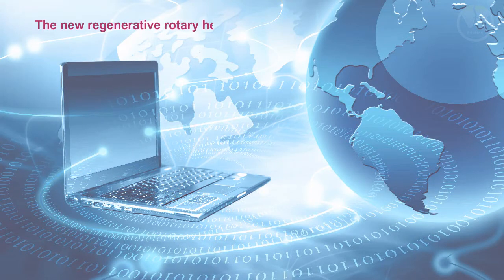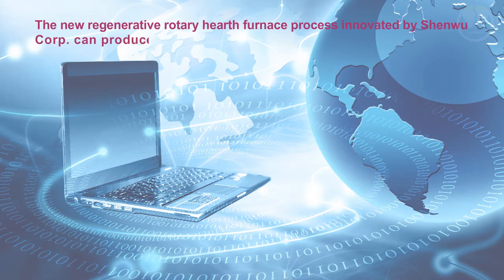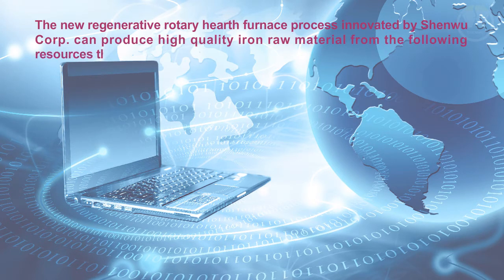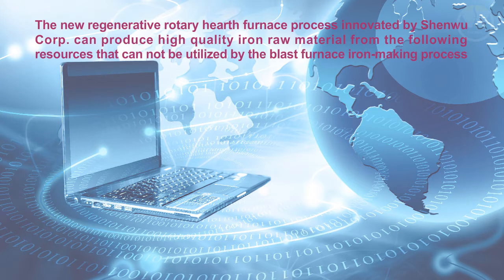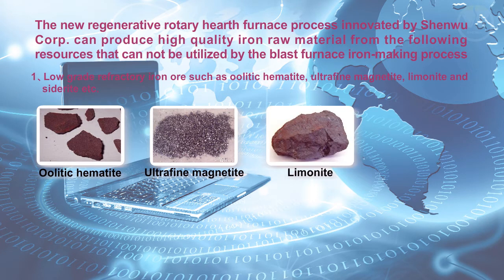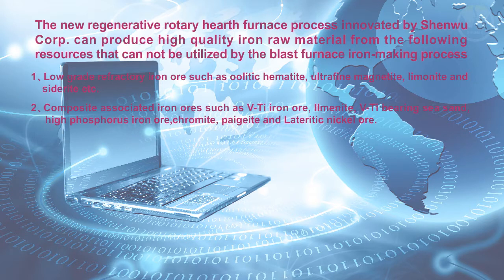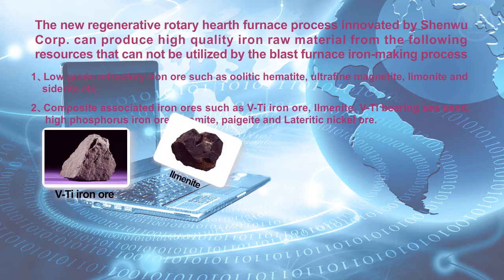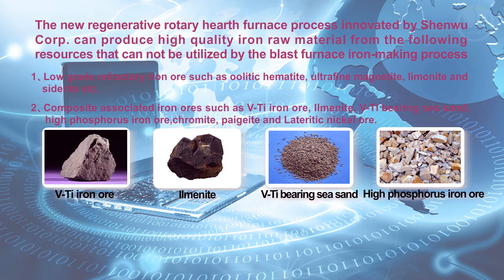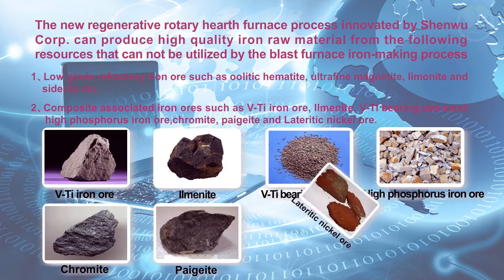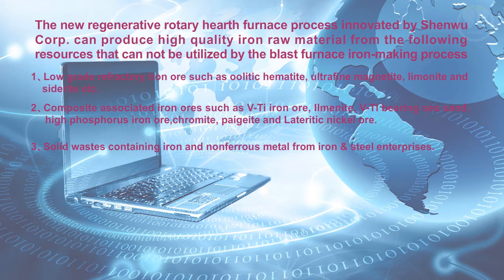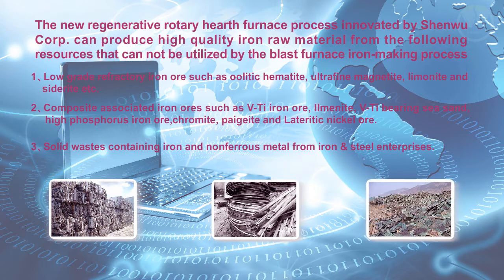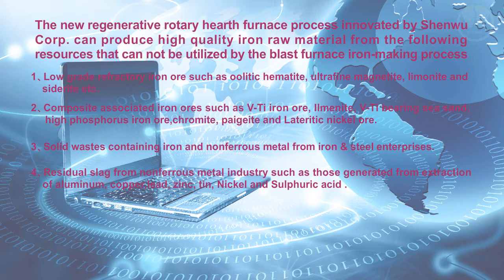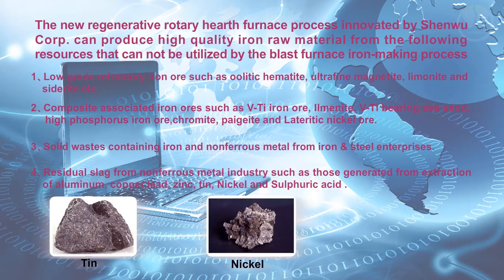The new regenerative rotary hearth furnace process, innovated by Shenwu Corp, can produce high-quality iron raw material from the following resources that cannot be utilized by the blast furnace iron-making process. 1. Low-grade refractory iron ore, such as oolitic hematite, ultrafine magnetite, limonite and siderite, etc. 2. Composite-associated iron ores, such as VTI iron ore, Ilmenite, VTI-bearing sea sand, high-phosphorus iron ore, chromite, paigeite, and lateritic nickel ore. 3. Solid wastes containing iron and non-ferrous metal from iron and steel enterprises. 4. Residual slag from non-ferrous metal industry, such as those generated from extraction of aluminium, copper, lead, zinc, tin, nickel, and sulfuric acid.